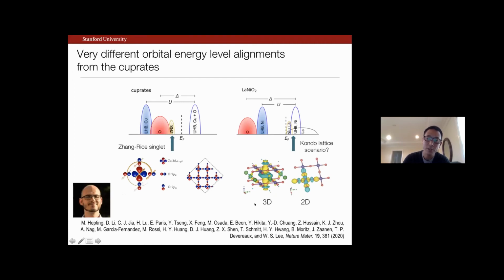And in fact, these early discussions led us and others to think about this being a potentially interesting analogy to the Kondo lattice problem, in that rather than a 4f level, you may have essentially this narrow upper Hubbard band in the midst of a more dispersing 5d band.